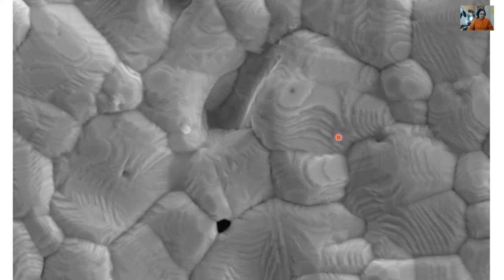Solid state grain growth is seen primarily in metals and ceramics, and particularly during a sintering process, so I can get some idea of how this material was processed by the presence of these facets. If you just handed me this micrograph, I would say this is either ceramic or metal, but I can tell you it was sintered. No melting occurred here because of the solid state grain growth.